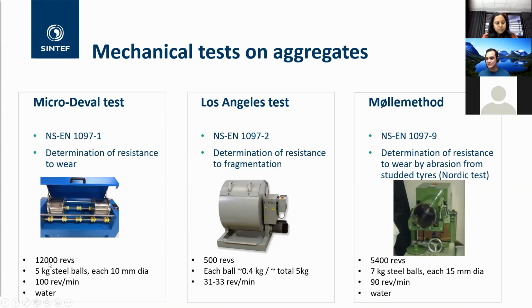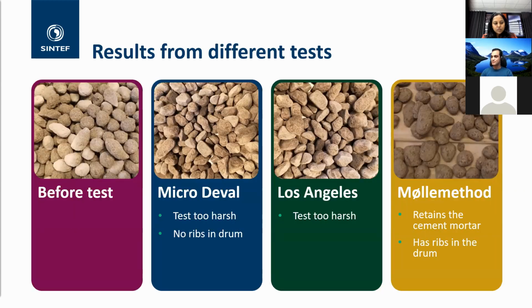As you see, these tests use some amount of steel balls, which are very hard compared to aggregates, especially our recycled aggregates after just 1 or 2 days of hardening. And they have a very high number of revolutions. So we thought that these tests might be too harsh for our aggregates. Obviously the Los Angeles test is very popular and known by everyone, and this test specifically we thought would be very harsh for the aggregates because of the heavy balls used and the high falling height of the aggregates. So first we tested all these different methods to see if we can use them.